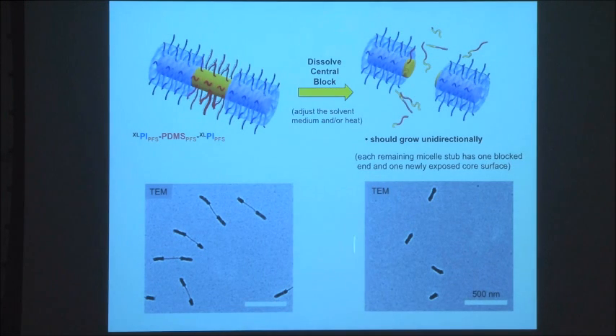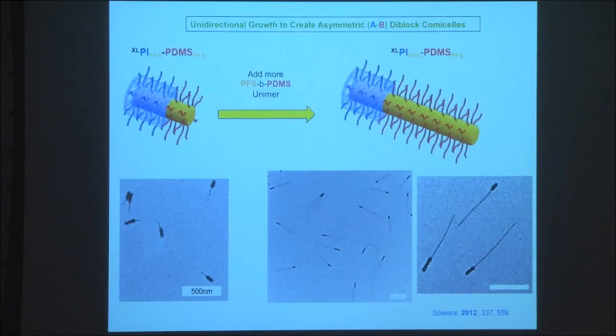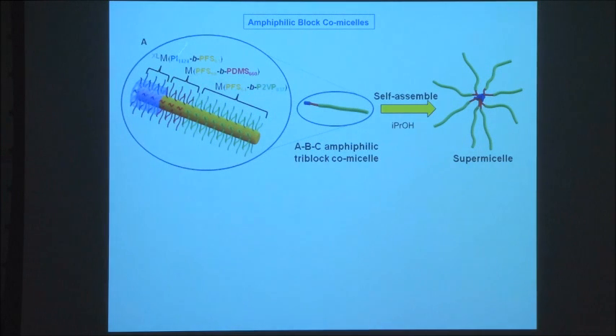So you take these and add more unimer to them, and what you find is they then grow in one direction. So if you add to these more PFS-PDMS, they will grow, and you can make AB block comicelles, as you can see here. And you can take these and now add PFS-poly-2-vinyl pyridine, and that will give you an ABC structure. And this is interesting because it's an amphiphilic block comicelle, so the P2VP end in green is hydrophilic. The other two blocks are hydrophobic, so this end is hydrophobic. So if you put these in isopropanol, these should self-assemble through the PI and the PDMS end to give you core shell structures, which would be supermicelles.